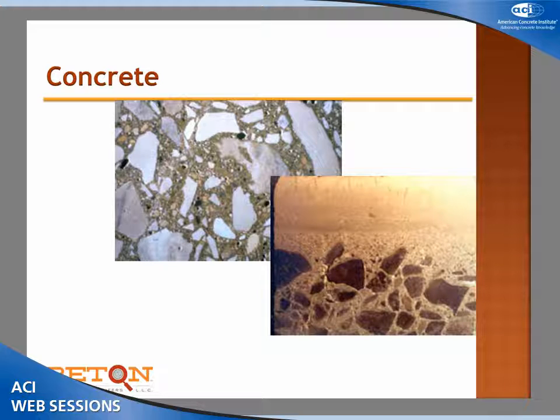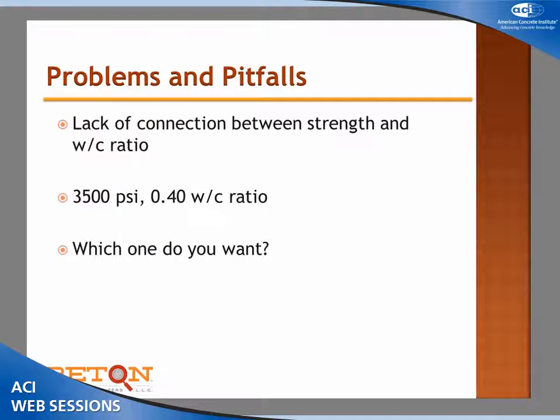It's really nicely segregated itself, but because I was out of town and they didn't notice, they tear it out, they cut it here and they broke it, and it met the compressive strength requirement. So then they called me and said, what the hell do we do? It meets the compressive strength requirement. I said, can you still scratch the surface with your fingernail? 7 days old. Yes. So then you should tear it out. What do you think is going to happen when you put trucks with studded tires across it? It's going to be a problem. Compressive strength, a very bad number.